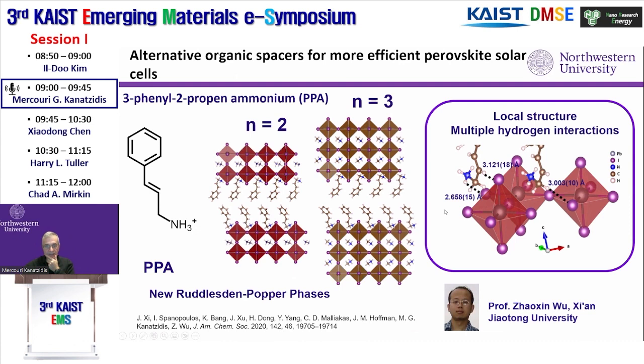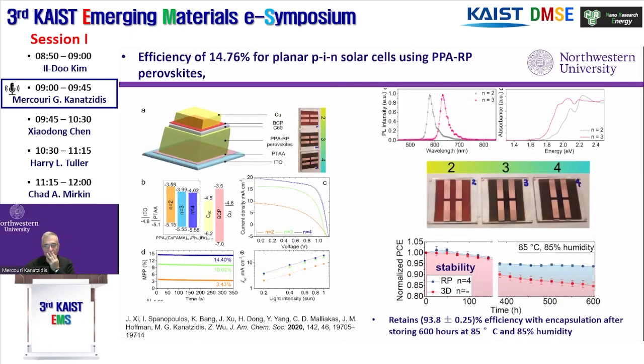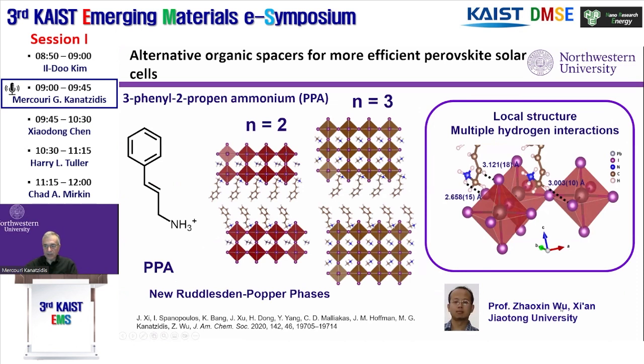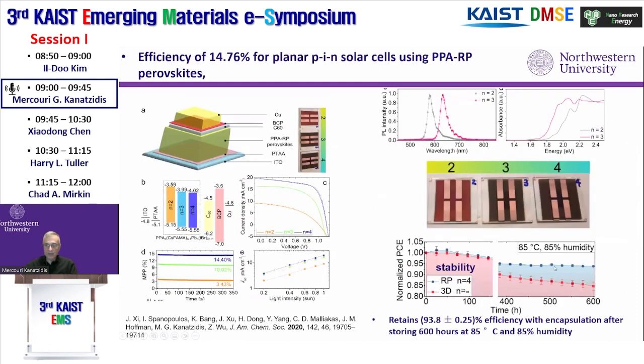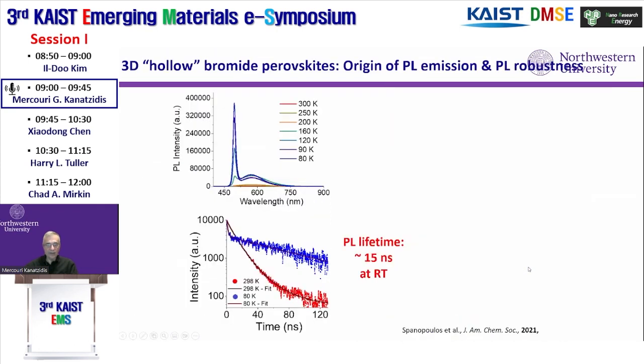So these are, as I said, quite interesting materials. They're flexible. You can make different organics, and you can actually tune the properties by intercalating them in between the layers. And again, almost every group, this is not our work. This was done by Professor Zhaoxin Wu at Xi'an in collaboration with us. Every group is reporting far better stability when the 2D, 3D system is combined and gives you a solar cell.